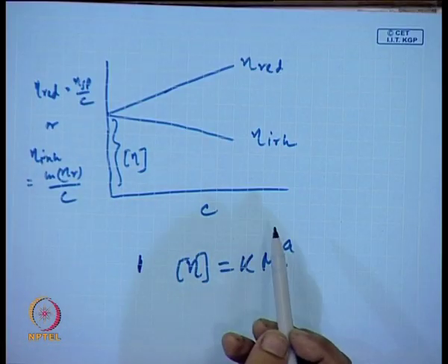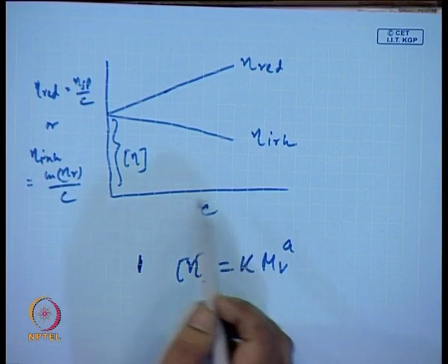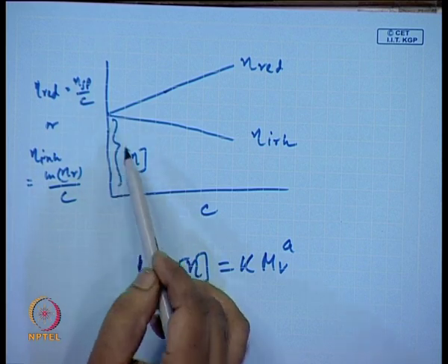If you measure the efflux time of the solution and the solvent, from the ratio you get the relative viscosity, and from that the reduced and inherent viscosity. So, you make solutions of different concentration, plot, and get the intrinsic viscosity.